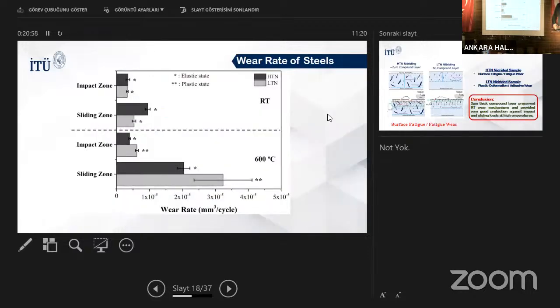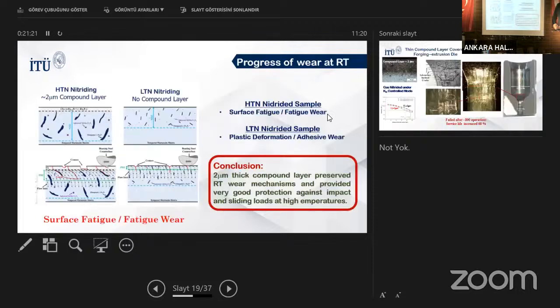Those are the wear rates that we have quantified. This is the wear rate of the impact zone and sliding zone at room temperature and high temperature. But since we are dealing with high temperature operations, it is very apparent that the high temperature nitriding has higher wear resistance compared to this. I'm skipping those.